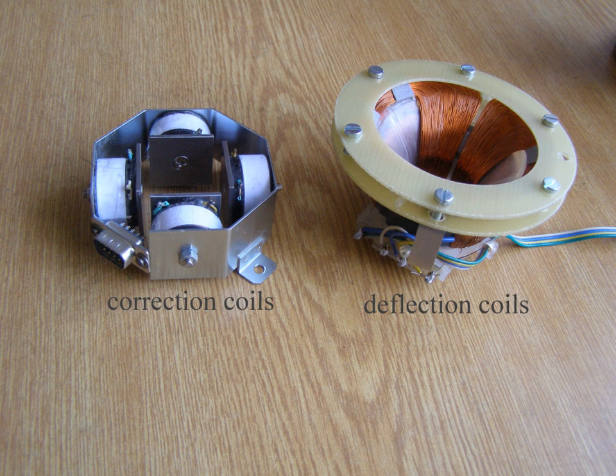Values of power density in the crossover focus of the beam can be as high as 10⁴ to 10⁶ W per square millimeter. Shallow penetration depths are in the order of hundredths of a millimeter. This allows for a very high volumetric power density, which can reach values of the order of 10⁵ to 10⁷ W per cubic millimeter. Consequently, the temperature in this volume increases extremely rapidly, 10⁸ to 10¹⁰ K/s. The effectiveness of the electron beam depends on many factors.